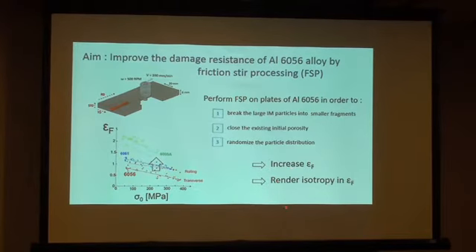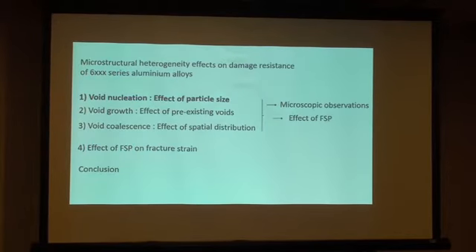And so the goal of this is to break the large intermetallic particles that are present within the 6056 alloy into smaller fragments, since it will increase the nucleation stress. We should also try to close the existing initial porosity, which will increase the ductility, and randomize the particle distribution, which we hope will suppress the anisotropy of the fracture strain. So now we go to the results.